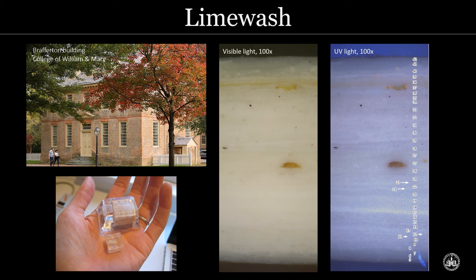The analysis of lime washes is really complicated because the material is so thick and brittle and it tends to break apart as soon as you use your scalpel to collect your sample. It's so frustrating. So you need to take larger samples. This isn't always possible. And I need to cast them in much bigger resin cubes. So in this image here on the bottom left, you can see I'm holding a typical paint sample, which is about 1 cubic centimeter, and a lime wash sample, which is almost 4 times the size.